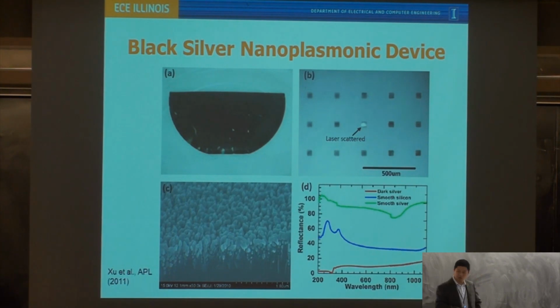We can also combine with the photolithography to only make those nanostructure on some defined region. Here you see we can basically make an array, actually small square array of nanostructures. Within the actual square, you can expect you have this kind of nanostructure, but outside the square, you have completely smooth film. Okay. As you can see here, if you shine a laser on the surface, you can see very shiny spot, very shiny scattering spot.